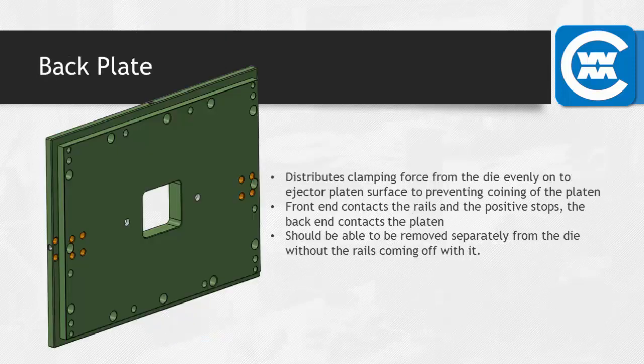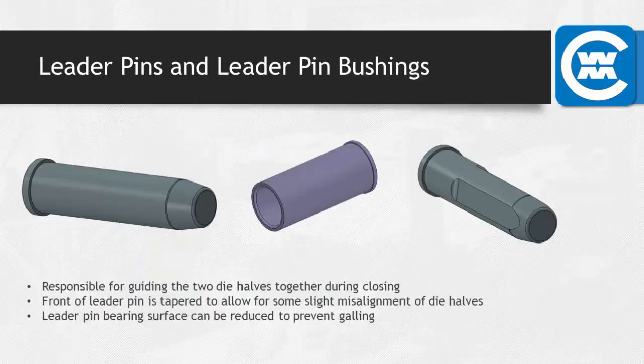The back plate, which touches the rail or is in between the rails and the platen, distributes the clamping force to the machine ejector platen. Otherwise, you risk clamping with high pressure to just the support pillars and the rails, and this can cause what we call coining of the machine platen and will cause the platen to be out of flat. You'll actually get divots where you're pressing and clamping under high pressure. It's an optional component for some die casters, but we feel it's necessary to keep our dies and platens in good shape. All right, leader pins and bushings.